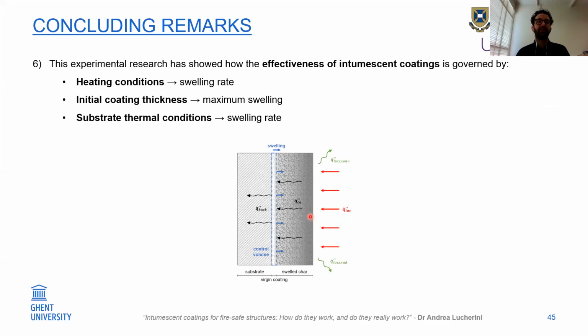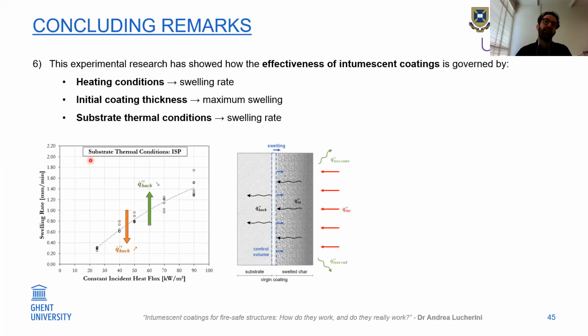The initial coating thickness controls the maximum swelling of the coating, and the substrate thermal condition, again, controls the swelling rate. So if this is the whole system, I have my incident flux at the surface, the heat that penetrates and reaches my coating that is swelling, and also some losses at the back due to the substrate. With the same substrate thermal conditions, so an insulated steel plate, for higher heat fluxes you get higher swelling rates. But what happens if you change the losses at the back? If you have higher losses at the back, you get a lower swelling rate. Instead, if you have lower losses at the back, you have a higher swelling rate.